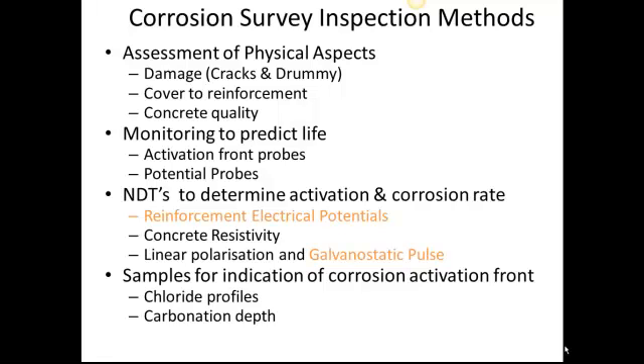It's possible to monitor the rate at which the front of chlorides, carbon dioxide, or other corrosion initiators travel. This can be done using probes, which are steel electrodes embedded at various heights in the concrete cover. When the front reaches them, they will begin to corrode, and this can be monitored electrically. It's also possible to determine it through destructive testing by taking carbonation depths through coring and using indicators, or chloride profiles through drilling and sampling.